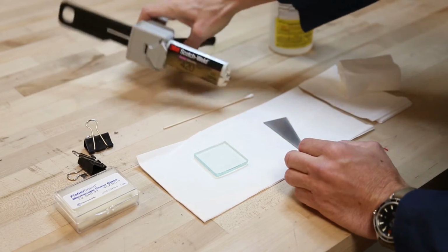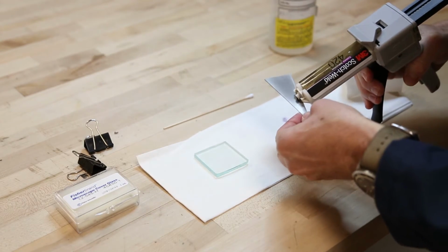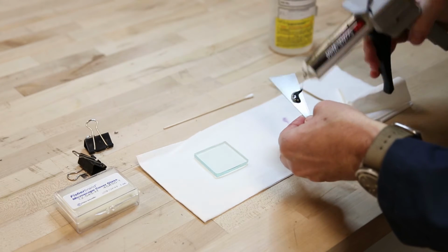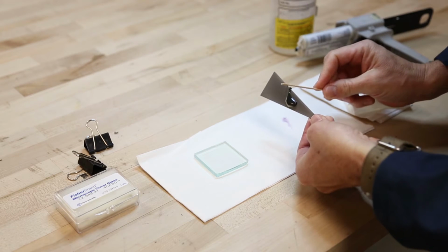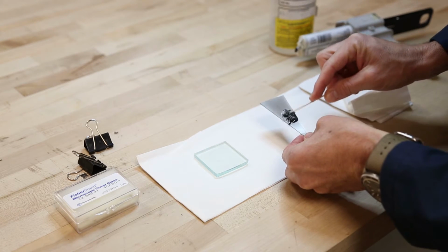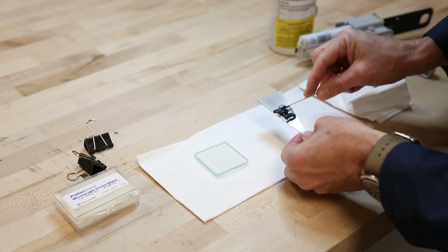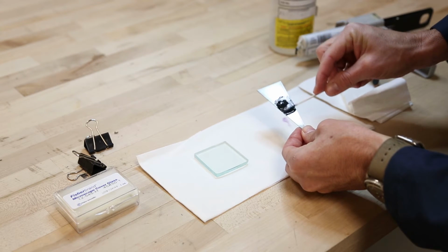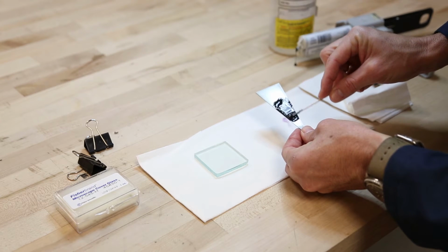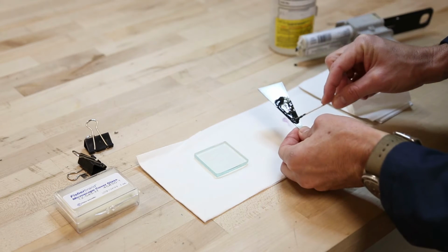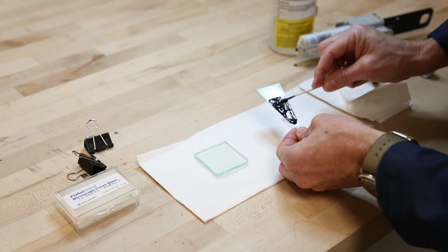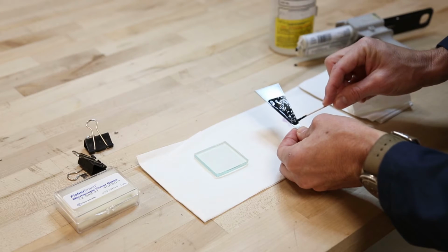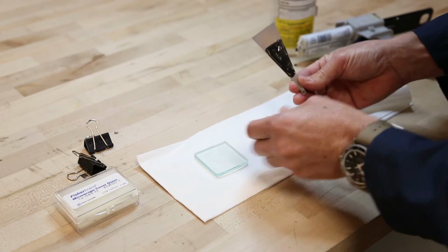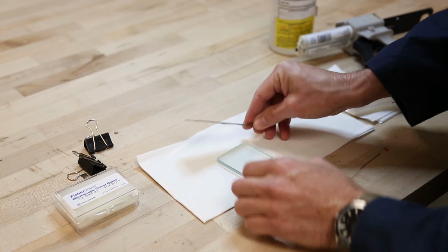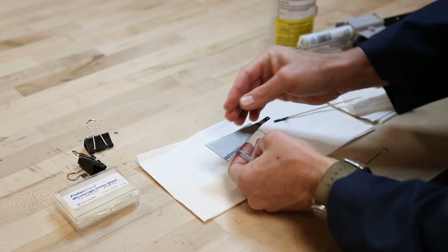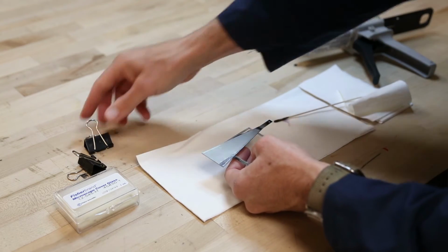And then I like to both dispense and mix the epoxy right onto the beam. Because the coupon here is pretty small, I don't need to cover the entire beam with epoxy. And for these coupon level measurements, I like to have the handle of the beam, the part my fingers are holding, overhang the edge to start the test. So I won't cover that either. Should about do it. I'll place it off to one side of the coupon, and that will make it easier to clamp down to my platen or my bench when I do the measurement.